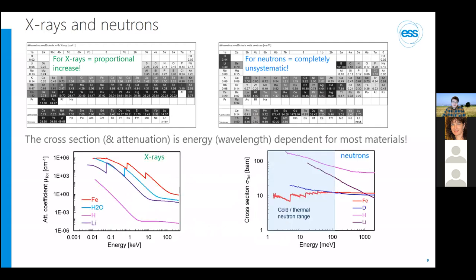What you may not have seen in some of the earlier seminars, however, is that this attenuation, or more generally speaking, the cross-section, also depends on the energy of the radiation. This is true for X-rays and for neutrons, and of course, one can make use of this during experimental investigation. The total neutron cross-section describes the observed attenuation by a material, and it depends on different scattering contributions as well as absorption. The scattering contributions can then furthermore be subdivided into elastic coherent, inelastic coherent, elastic incoherent, and inelastic incoherent scattering.